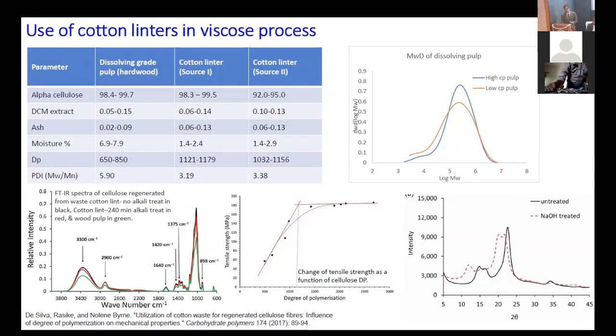And because of the high DP and high crystallinity, it limits the reactivity of cotton pulp to the NaOH, which is the first treatment that we give to the pulp, and subsequently in the xanthation process. The good point is cotton has a very narrow polydispersity index, and this is something we always go for, pulp which has a very narrow molecular weight distribution. If you see the first graph, even after the alkali treatment, the crystallinity of the cotton does not drop significantly to the level it should drop for wood pulp, and this is a challenge.